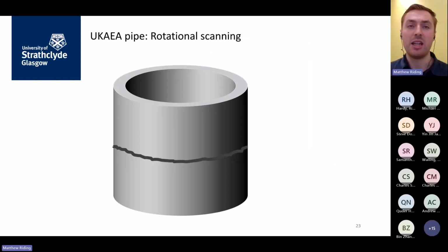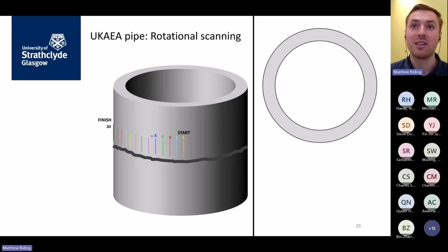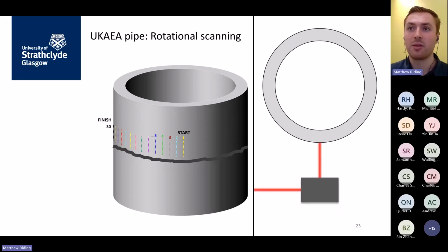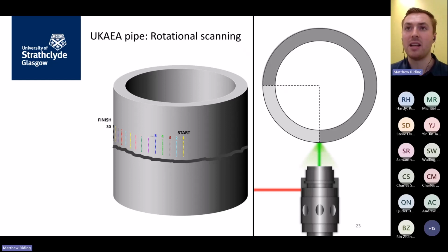In terms of scan strategy, at this time we actually captured a series of images. So we started at one position on the surface, the outside surface of the pipe, and then took a second array image at a next location, and then took a whole series of images covering a 90-degree sector of the sample. Just to be clear on the laser configurations there, we've got the lasers coming in from the side stacked above each other, and then focusing on this 90-degree sector.